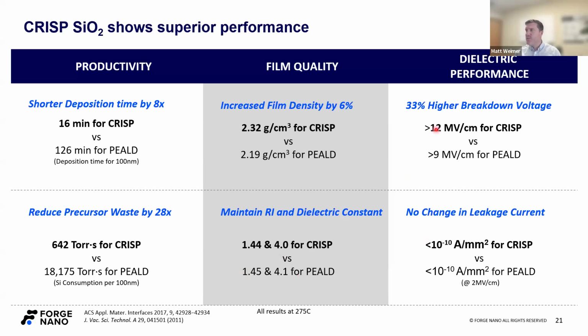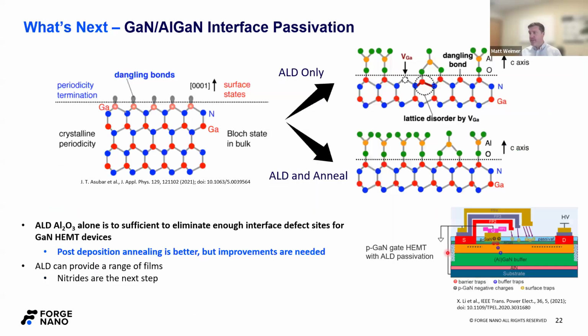But again, I think this last column is really where our film stands out. And as I showed on that previous slide, the breakdown voltage is quite high. We've measured it above 12 on silicon features, like metal insulator metal capacitor type features. And the leakage, they're pretty comparable. That's one of the places where plasma enhanced ALD really shines. Okay, so the last application that's already out there for GaN specifically is surface passivation.